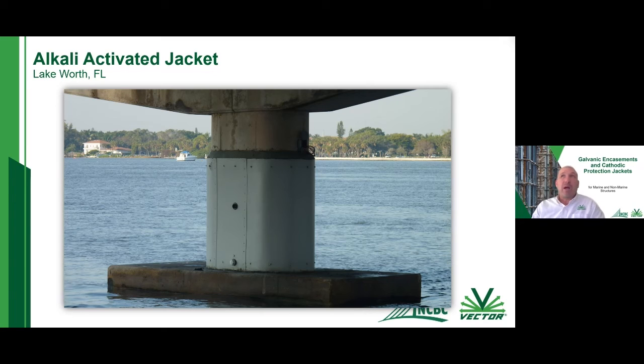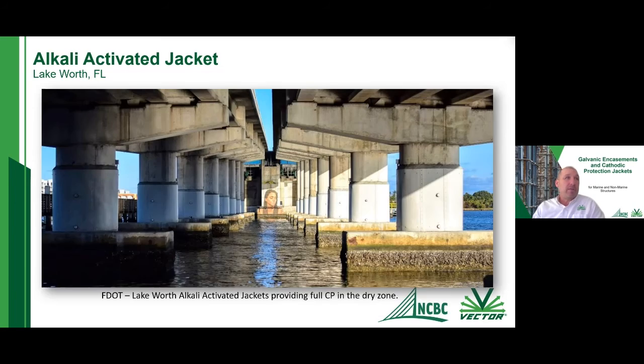So again, this is a finished picture of the pile. So you can see the tide at low tide and high tide. So the tide never gets up to the jackets here. So it's just being activated by the anodes within the jackets. One thing to note here as well is not only did the columns receive cathodic protection from these anodes, but those footers that you can see the columns sitting on, those were actually receiving CP from those anodes as well.